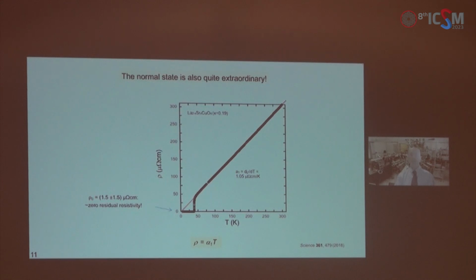For one thing, resistivity can be linear in temperature very accurately. This was known already in 1987, but remarkably, it remained true till today. What I'm showing here is a lanthanum strontium cuprate film, a very good one, grown atomic layer by layer by molecular beam epitaxy. As a figure of merit, you can use the residual resistivity ratio, the ratio of the resistivity at room temperature over the extrapolated zero temperature resistivity. Here it's more than 200.